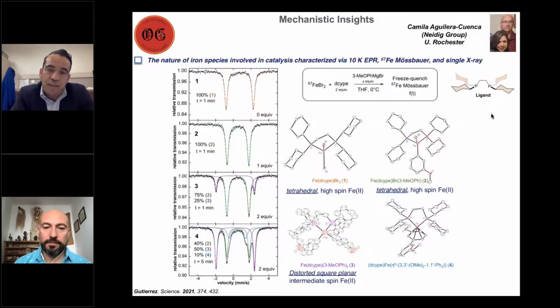So what you really need is to get as much experimental data to then calibrate not just one species, but several different species that you've seen are active or relevant in catalysis. And then if you're able to mimic and explore that, then you're going to be okay. But I think focusing purely on computation is not going to be practical, not for this transformation, because everybody knows that the spin states are very sensitive to the methods. Okay. Well, thank you so much again, Osvaldo. Yeah, thank you.